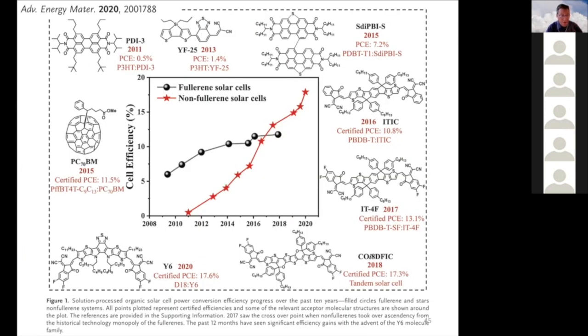Now, recently, the focus has shifted from fullerene acceptors to other molecular components. And here we see that recent efficiencies have even reached about 18%. Around 2016, the non-fullerene materials overtook the buckyballs, and they used these rather special conjugated acceptor molecules that absorb a lot of light, but they also give charge separation and a small driving force. So there's only a small offset in energy relative to the singlet excited state. But you see that all four of them are a certain class of molecules. So they are highly conjugated. They have cyano groups, so there's acceptor groups, there's donor groups in the middle, a lot of solubilizing alkyl tails. And so this is the recent development in these fields.